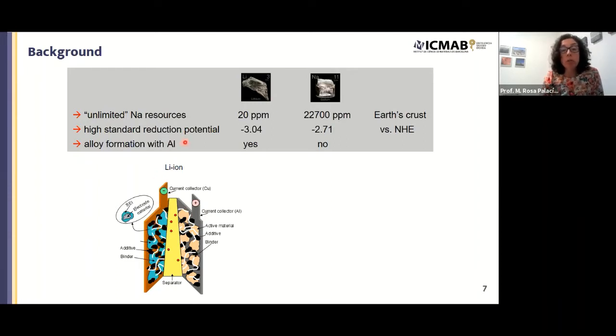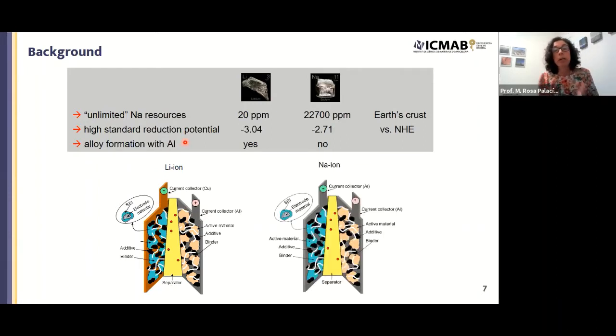In the case of sodium, this is not the case, so ideally you can use aluminum as current collectors for both the positive and the negative electrodes. And this, in principle, could also enable the transport of those batteries short-circuited. And this would release some of the restrictions for the safe transport of batteries. This is something that is still being checked, especially by startup companies building those cells. But this is really an interesting advantage.